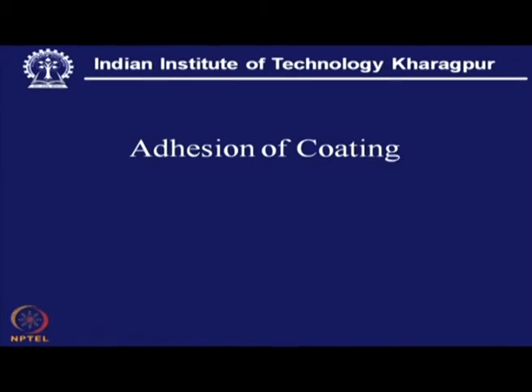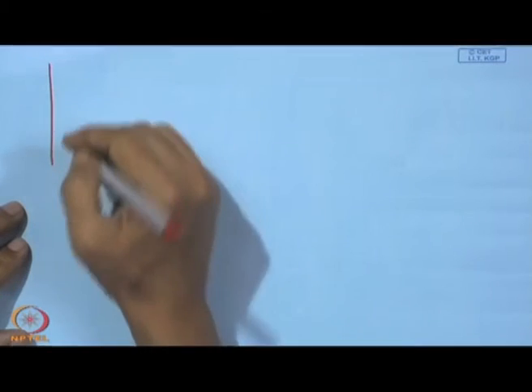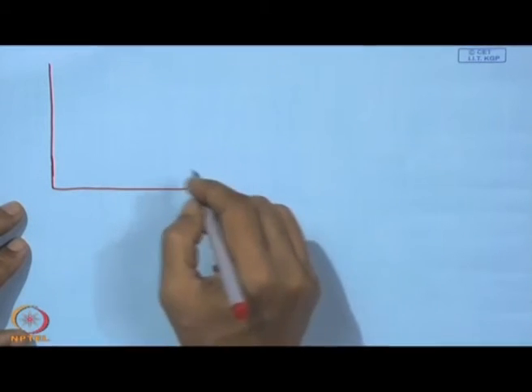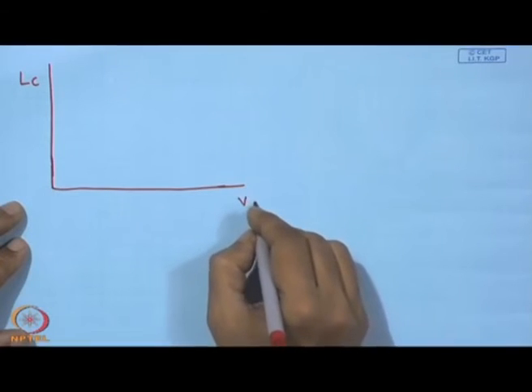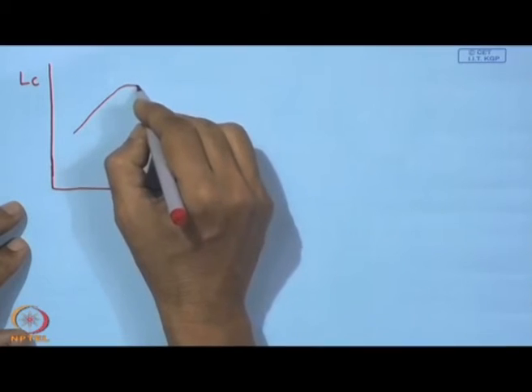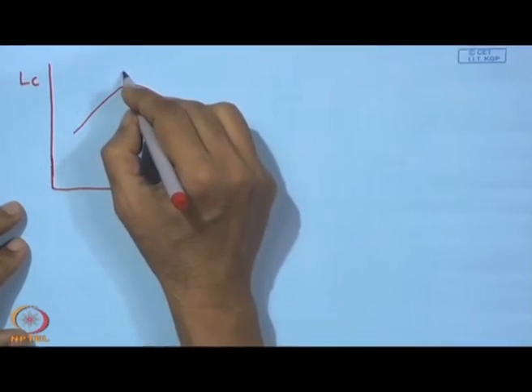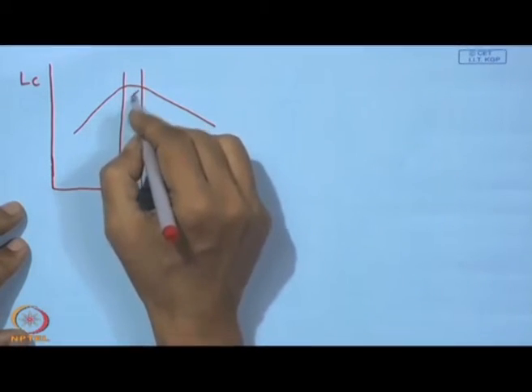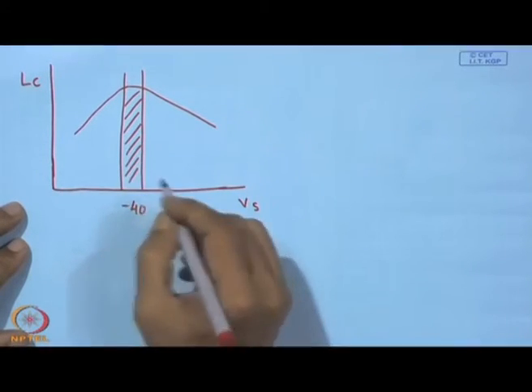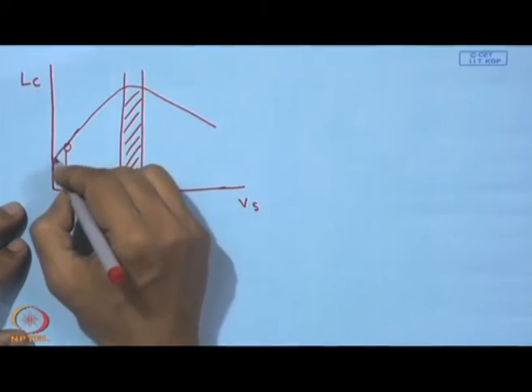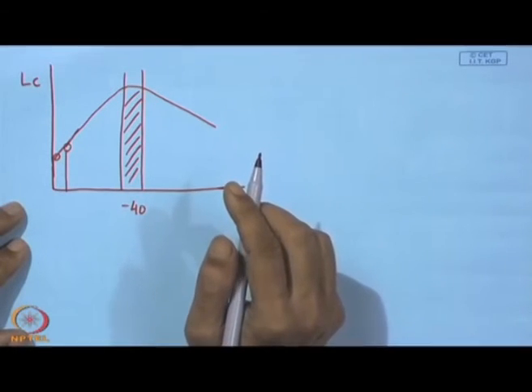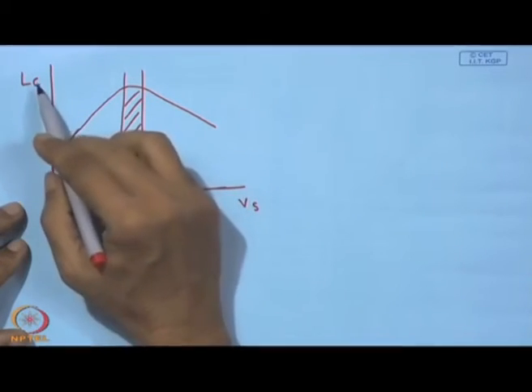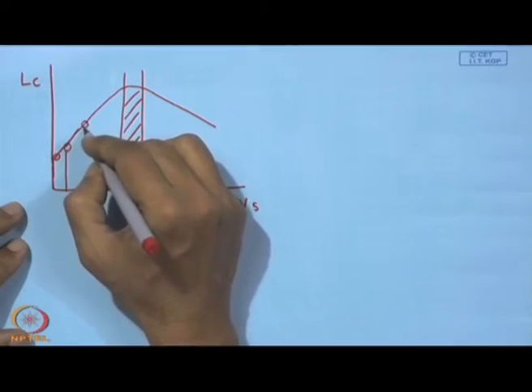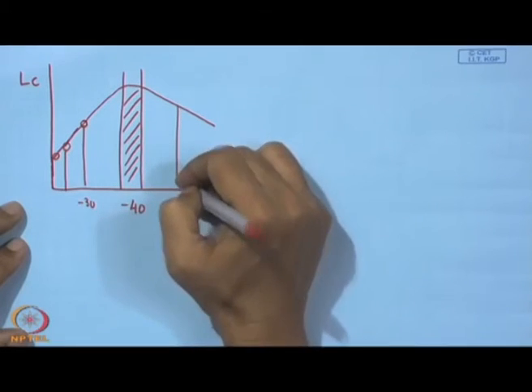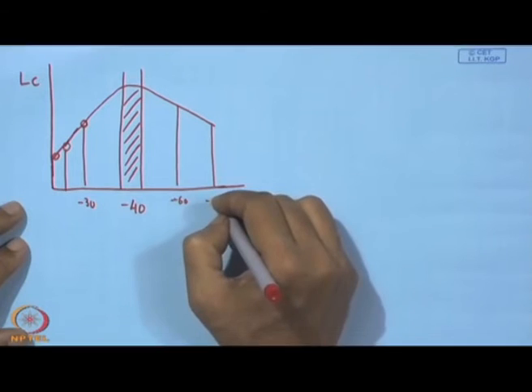Similarly, what we can do is look at the adhesion of the coating. Now, adhesion of the coating is the most important property one should look for. So, this is Lc and this is also bias. Here also we see that this is going to be a graph of this nature, and this may be a zone which will be of immediate interest, and it is around minus 40 volt. This is actually 0 volt. So, at about 0 volt we have one of the lowest Lc values, that means the critical adhesion strength, and this may be around 30, but on this side it is minus 60, and this is going to be minus 90.